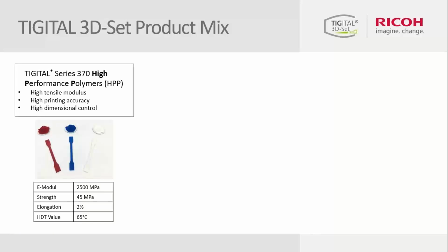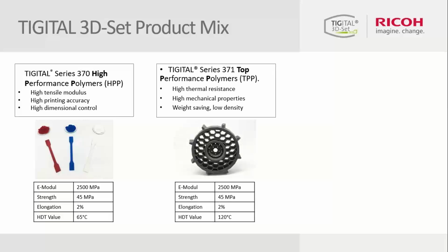The first one is the high performance polymer, which we showed also during the Formnext together with Ricoh in 2019. It has a high dimensional stability and accuracy, high tensile modulus with an HDT value of 65 degrees. And the second material of ours is the top performance polymer with high mechanical properties and high thermal properties. We have HDT A values over 120 degrees, and we can adjust the HDT value to your needs up to 140, 150 degrees.